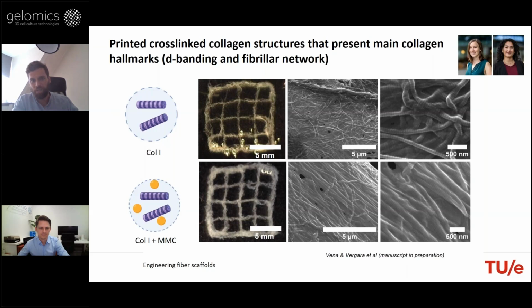No, that was actually a limitation that we had. We did these stainings over 3 and 7 days, and what we observed is that it's still a challenge that we have to solve: the fibers dry out over time, and since they are so small, they disrupt. So keeping these constructs over longer culture periods is something that we need to address, either by increasing the polymer content or by enhancing the cross-linking of the material.